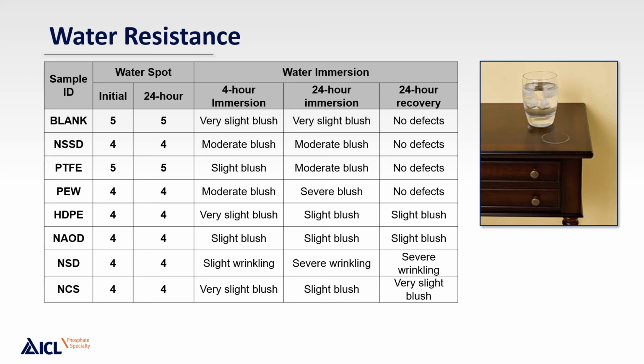And then after 24 hours of cure, it went through the water immersion test of actually putting the glass plate into an ambient water bath. Observations were taken at a 4-hour and 24-hour time frame. You can see here that obviously this resin system is not designed for glass adhesion, but there are differences between all of the additives in terms of level of blushing or wrinkling of the film.